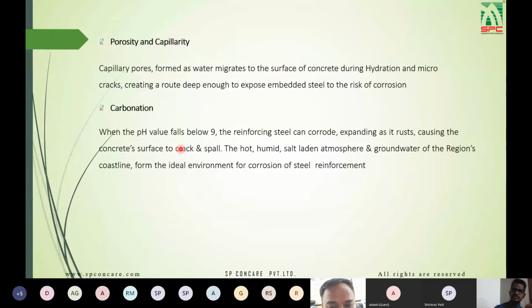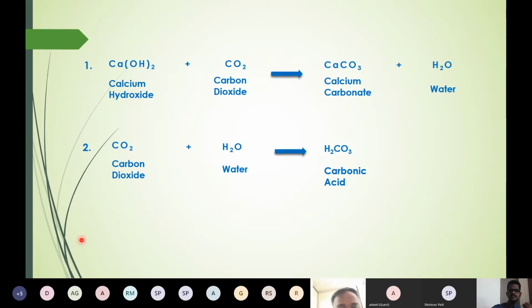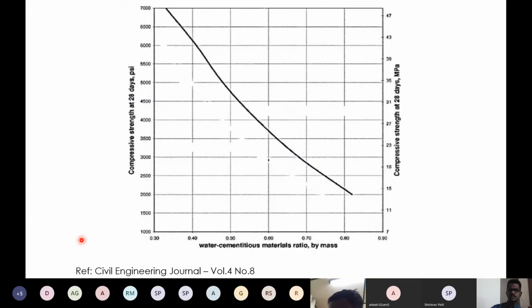So when the pH value falls below 9, the reinforcing steel can corrode, expanding as it rusts and causing the concrete surface to crack and spall. The hot, humid, salt-laden atmosphere and groundwater of the region's coastline form the ideal environment for the corrosion of the steel reinforcement. So these are the reasons why we need the admixtures.